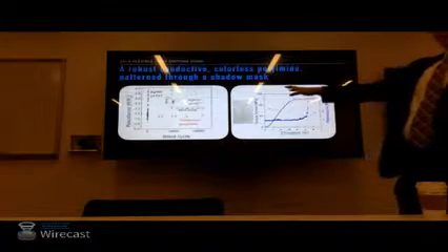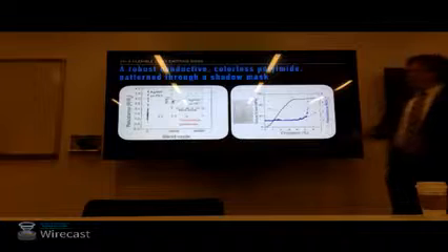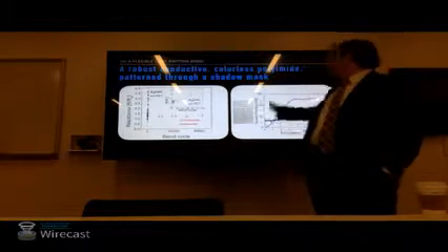So this is kind of our dog bone structure here. What I observed, I only ran about five of these, so certainly a more controlled experiment to characterize failure would be needed. However, what I observed somewhat repeatedly is that our resistance shoots up before our device breaks at about 6% elongation. But you've got a yield process, presumably. That's correct. So I guess you could say yes, it's failed, but not fractured.